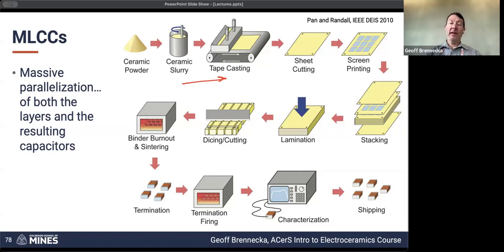So if you're doing this tape casting process with water and aqueous-based additives, that's a lot less expensive to deal with in terms of hazardous waste and disposal than if you're using organic solvents. However, a lot of times the organic solvents give you much better performance. They give better wetting characteristics and faster drying characteristics and less surface tension, so less stress during the drying and lamination, all these kinds of things. So it's always a big balance between trying to develop a new binder system that's aqueous or non-aqueous, because they have different challenges there.